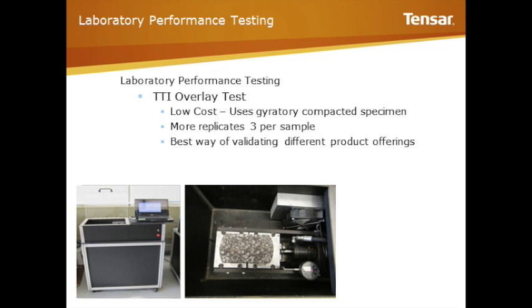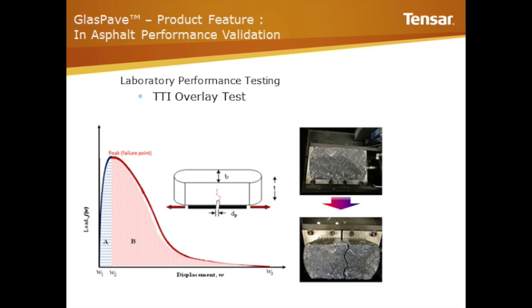And so what we decided is, well, we could use this technology. We've changed the way that the material is loaded. We use monotonic testing, and we also reduce the temperature at which the test is performed. Why do we do that? We do that so that we can actually improve the repeatability in the test, because we want to improve its sensitivity. And we also believe that at lower temperatures, we get a better understanding of the performance of the mix when it's more likely to fracture.